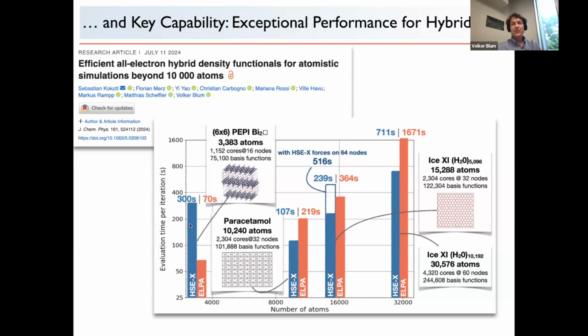But if you then contrast this to the other things in this image, suddenly the system doesn't seem so large anymore. There's a paracetamol crystal here, which is 10,000 atoms with somewhat more basis functions. So it's a much larger system, and you can see that in this case the eigenvalue solver outdoes the hybrid density functional part. We can do the same thing with forces, so then the time goes up a little bit more because we have forces in the game, but that can be done. And then finally, because he could, Sebastian demonstrated that we can also do something.